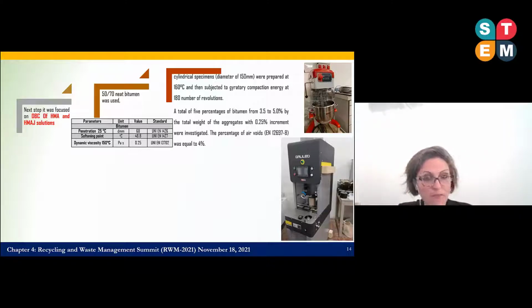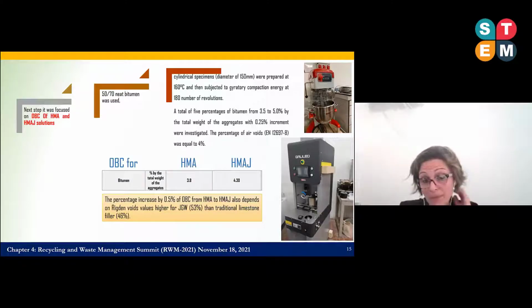So we investigated bitumen from 3 to 5% by the total weight of the aggregates, and the best percentage of bitumen was 3.8% by the total weight of the aggregate for traditional hot-mix asphalt. But when we reused jet grouting waste as a filler in complete substitution of the limestone filler, the percentage of bitumen increased, and it's in line with the Rigden voids value. This is important because the Rigden voids reflects the percentage of intergranular voids filled by bitumen.